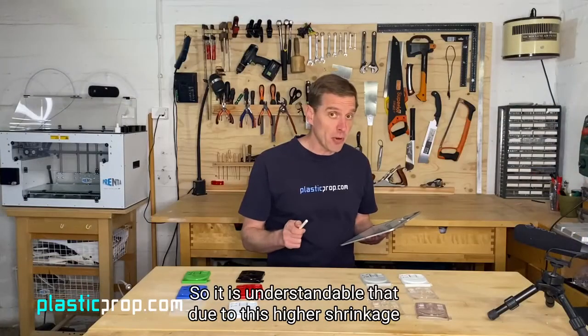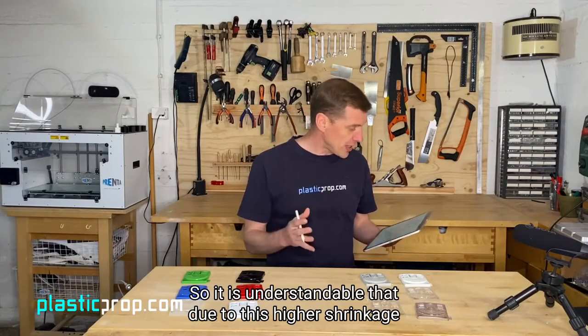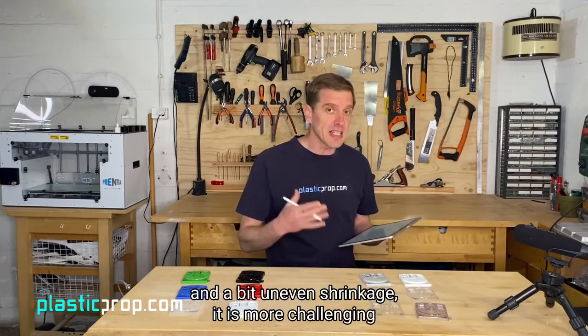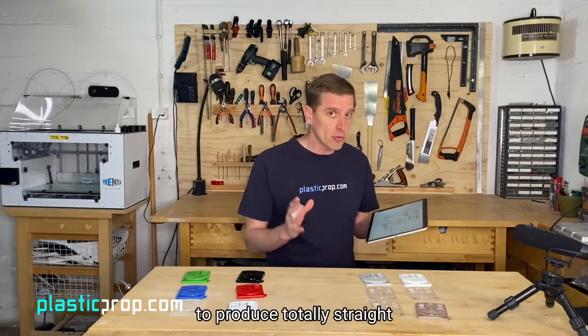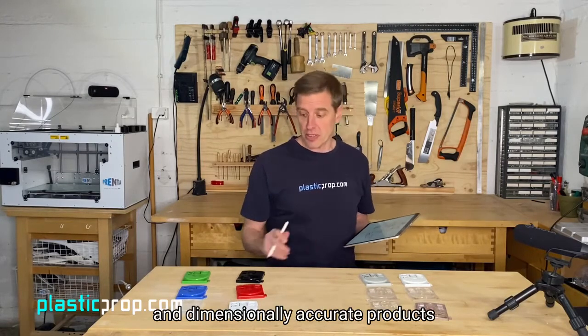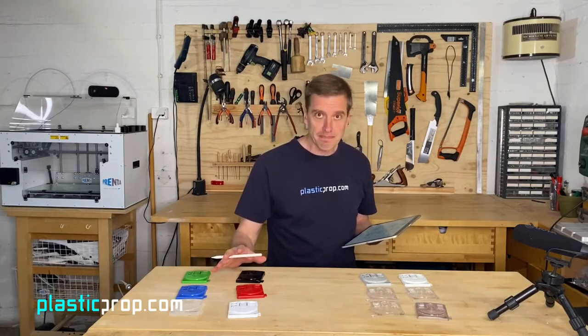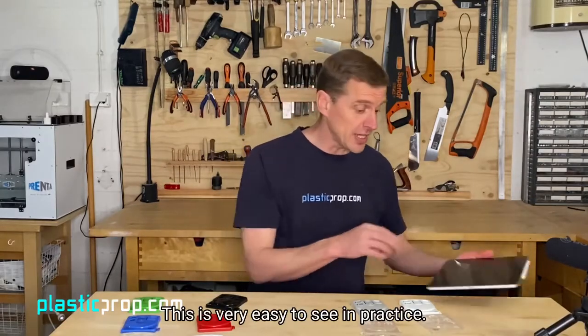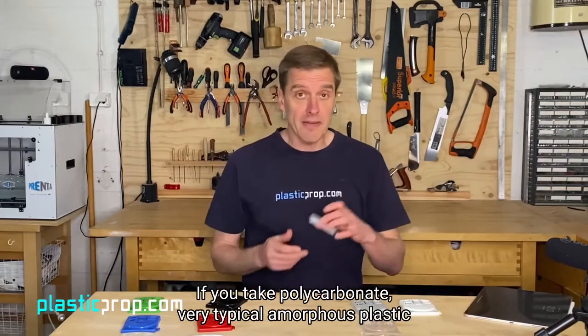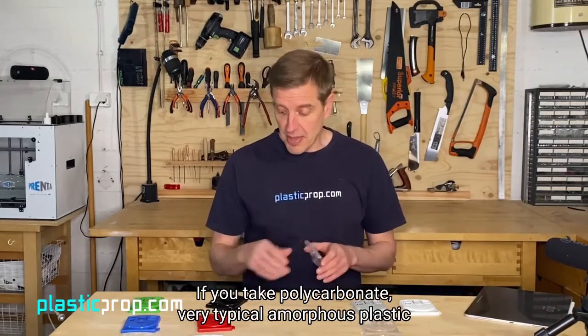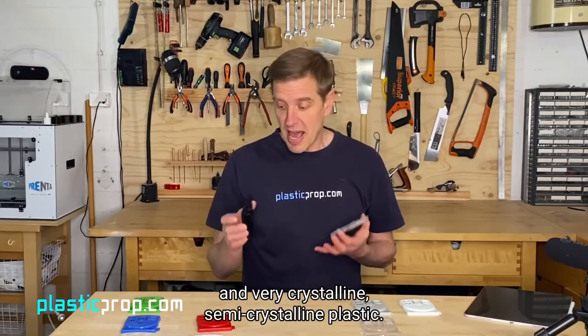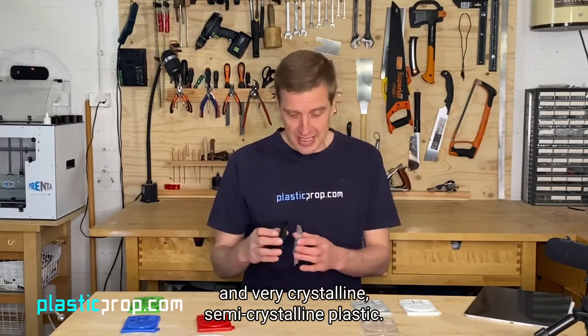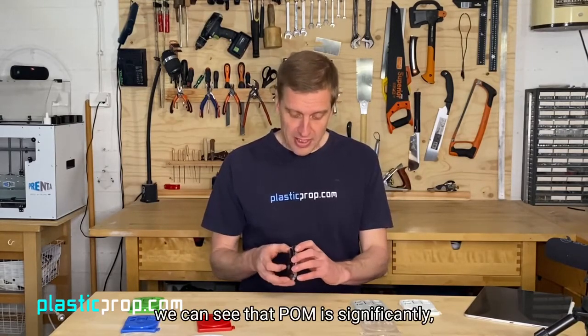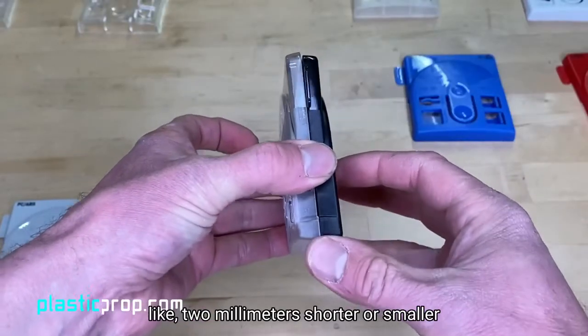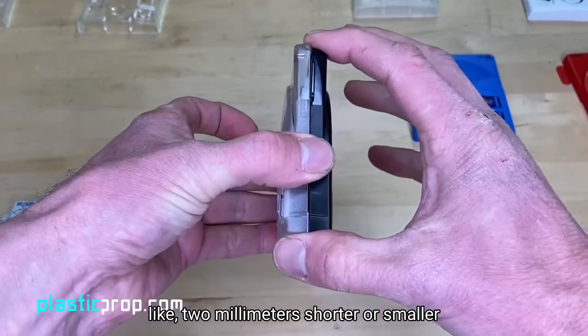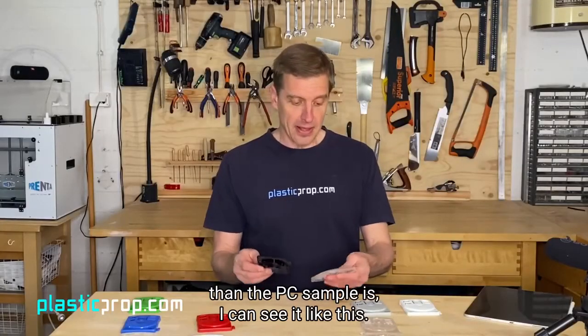So it is understandable that due to this higher shrinkage and a bit uneven shrinkage, it is more challenging to produce totally straight and dimensionally accurate products using semi-crystalline plastics. This is very easy to see in practice. If we take polycarbonate, very typical amorphous plastic, and then POM, very typical semi-crystalline plastic, and we compare their size, we can see that POM is significantly, like 2 millimeters, smaller than the PC sample is.